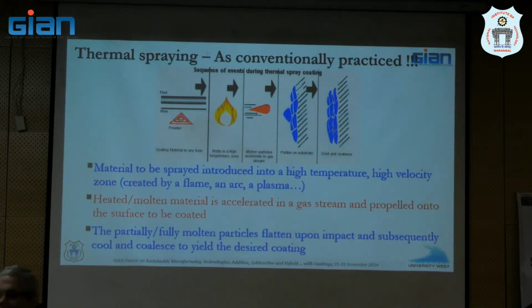What happens? It doesn't form a pancake very nicely, right? And it's coming at high velocity, so the middle part which is not molten can bounce back, because it's not spreading. Then what happens if it bounces back? That becomes a reason to form porosity in the coating, right? One.